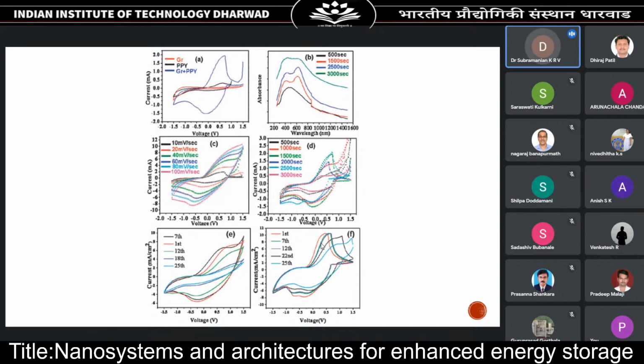So these are the electrochemical characterizations of the composite structure. You can see part A. If you use graphene alone, as shown by the red curve, this is the CV curve, the cyclic voltammogram curve. If you see the red graph alone, the area under the curve is very small. That is primarily because graphene has an electric double layer capacitance only. And then we have the polypyrrole, which is shown by the black curve. If you combine these two, you can see the dramatic improvement in the area under the CV curve. That is shown by the blue curve, which is graphene plus polypyrrole, right?